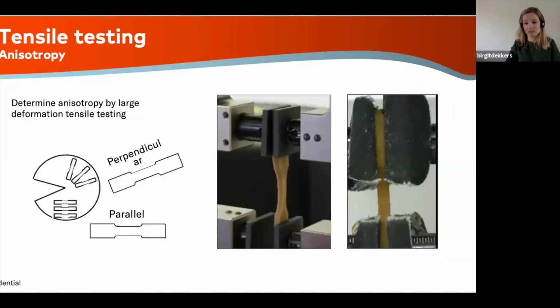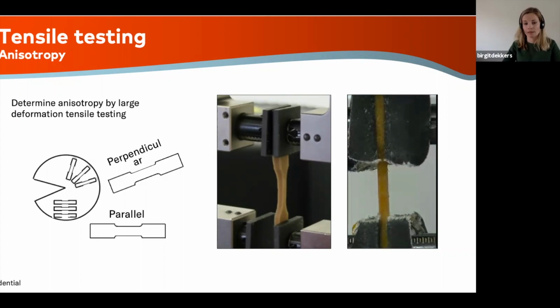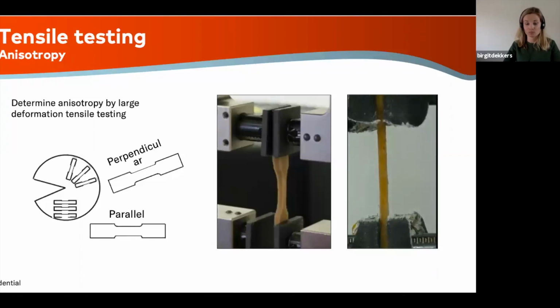One of the things that we then started doing is tensile tests. I hope I can also start this movie already. Basically taking samples in parallel and perpendicular to the shear flow, and then see how the material behaves upon stretching these types of systems. In the case you get a nice gel, the strength in both directions, in parallel and perpendicular, is the same. In the case of a nice fibrous meat-like texture, you see that the material strength is much higher parallel to the shear flow than perpendicular to the shear flow.